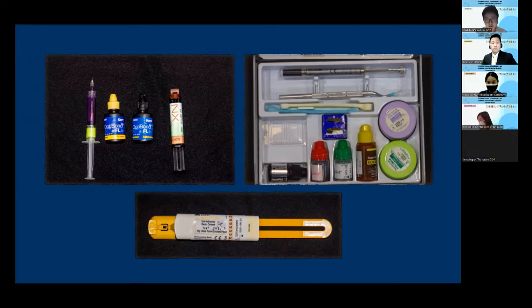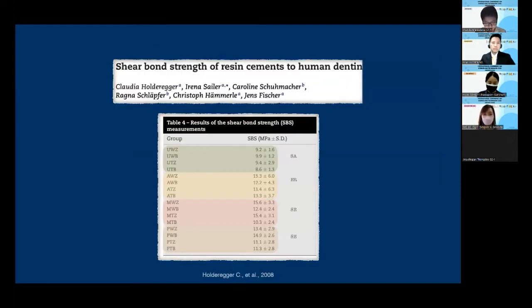Then the novel resin cement systems have been developed to simplify the clinical use, such as self-adhesive resin cement. They are less technique sensitive compared to the conventional ones. But the problem is that self-adhesive ones have relatively poorer bond strength to the tooth. The study in 2 centers in Switzerland compared the different resin cements, and this showed that the self-adhesive resin cement had the lowest shear bond strength compared to etch-and-rinse and self-etch systems.